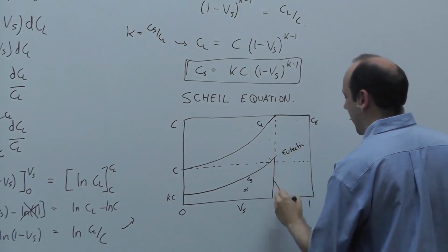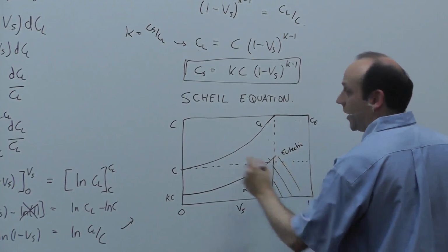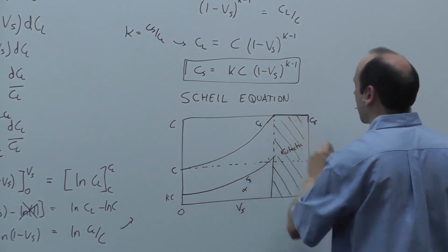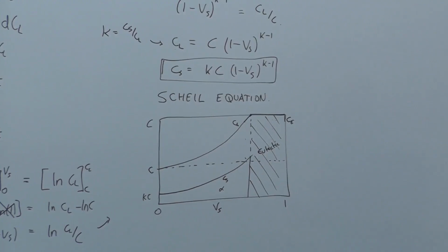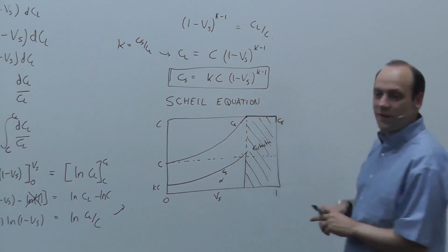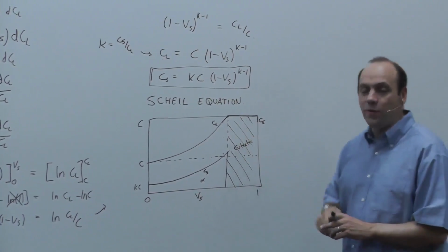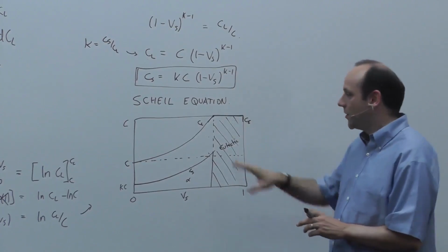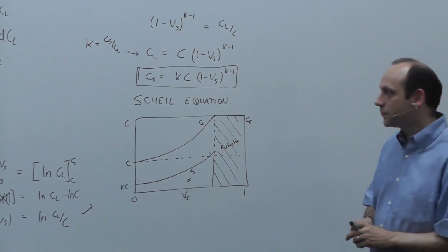So it becomes those plates of alpha and whatever it is, beta phase in our case here. So that becomes eutectic at the end. And because this equation goes off to infinity, you'll always get a eutectic here in a binary eutectic phase diagram that's solidifying under Scheil.